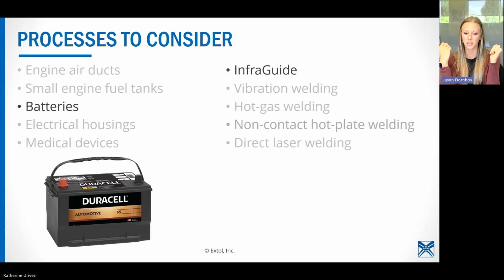And then direct laser welding, the tooling gets complex because you don't want to tip your battery on the side. Size becomes an issue. And then because battery walls are so tall, you often get warping or bowing of the walls. And your laser profile is set to one area. So if that wall is warping outside of your weld profile, then you're not going to get any melt in that area. So you risk the lack of hermetic seal in the assembly.